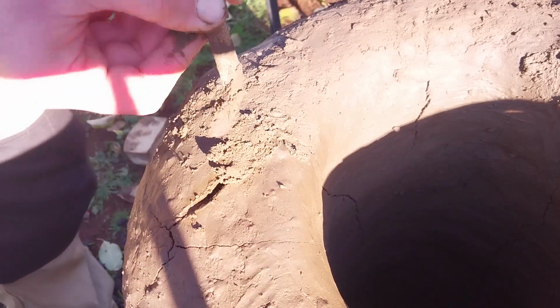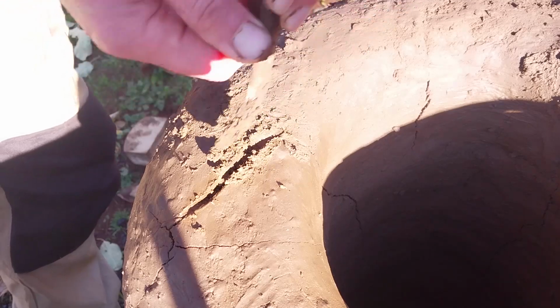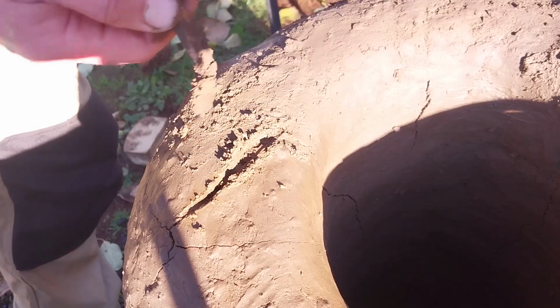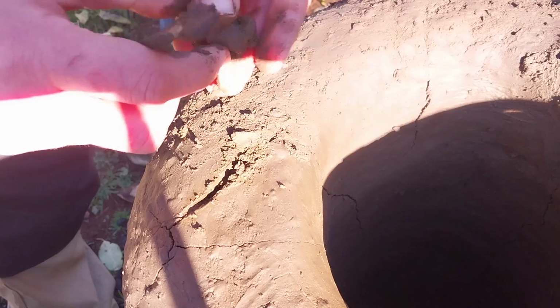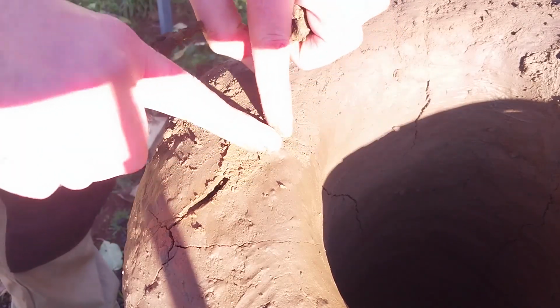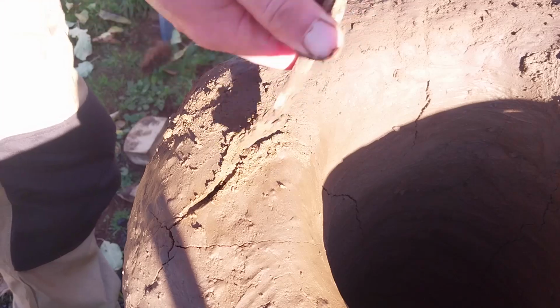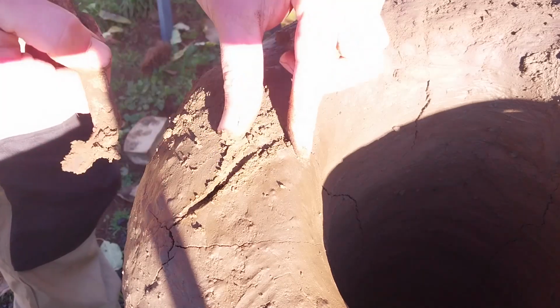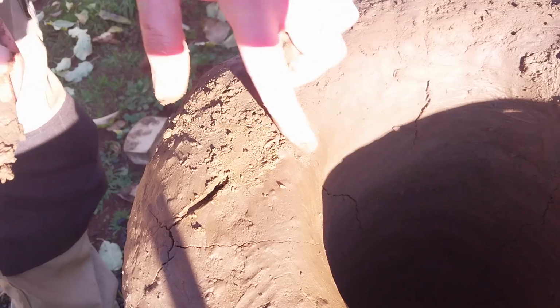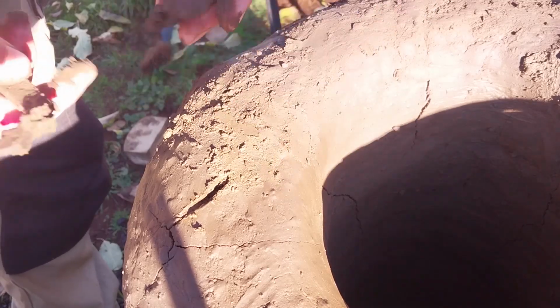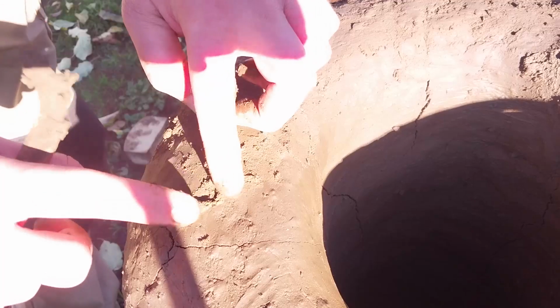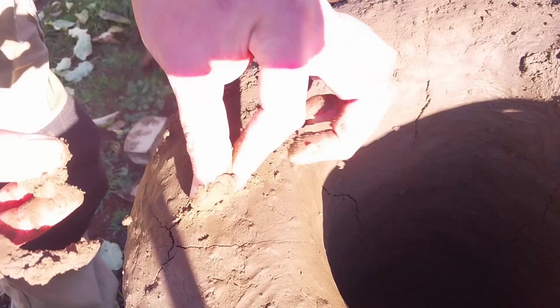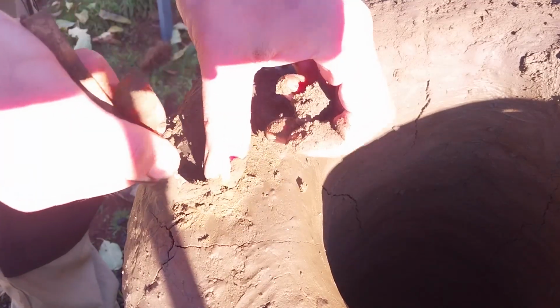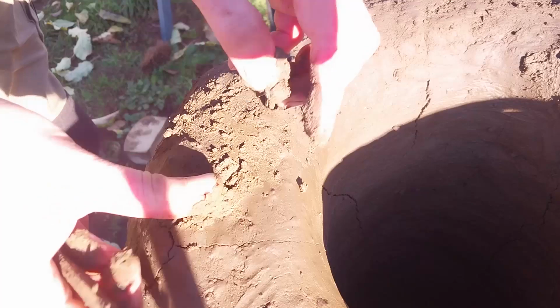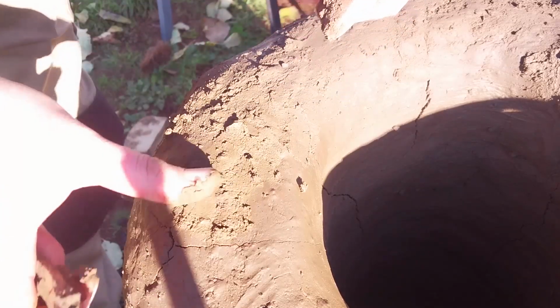And with half of it in there, you can use the back of the tool to follow the crack, and that will push that layer of clay down in. And then we do it again. Back of our tool, you can see it doesn't go down as far this time. And then this time we can just push it over. And we just do that the whole way. Pushing it down in is essential, otherwise you're just putting a band-aid on it. And we don't want band-aid fixes, we want a solid foundation again.